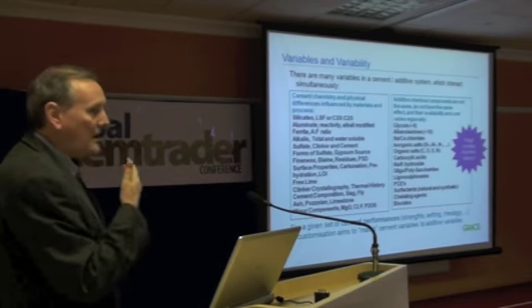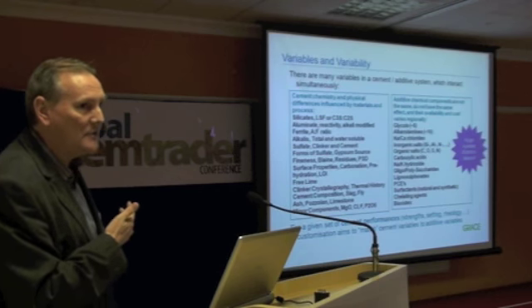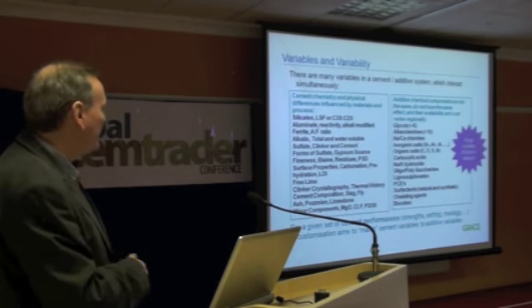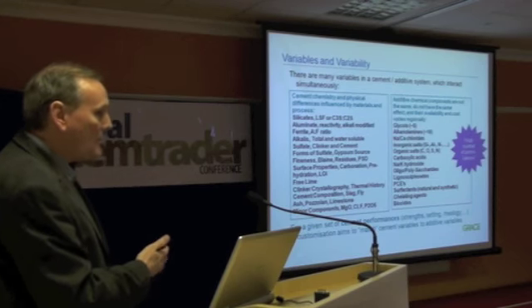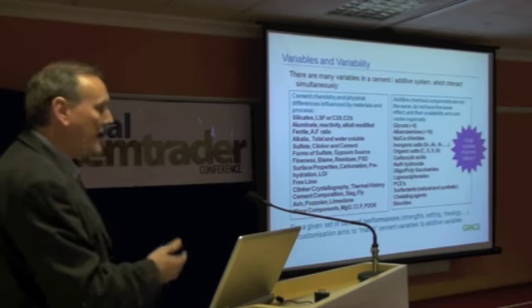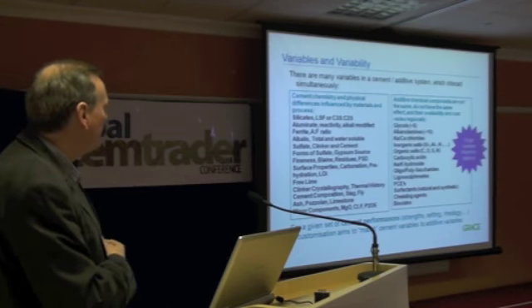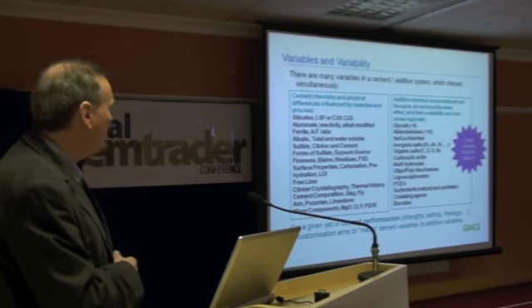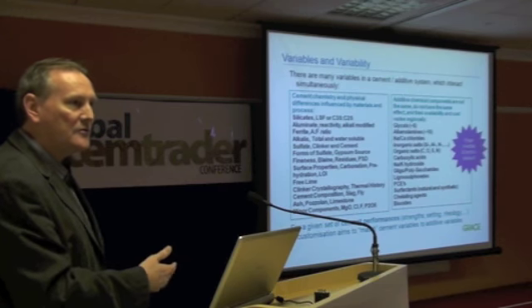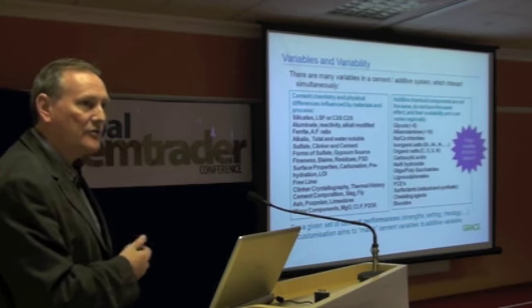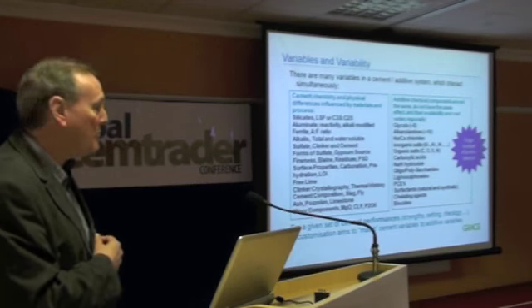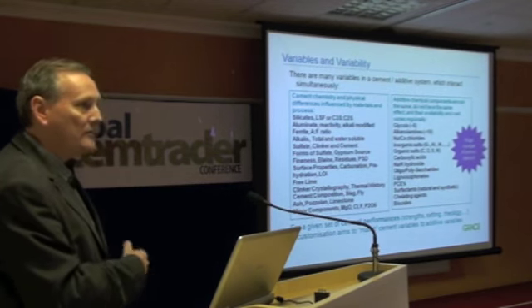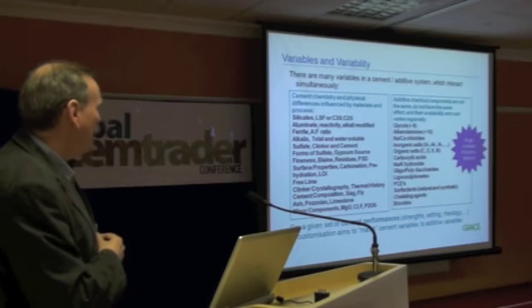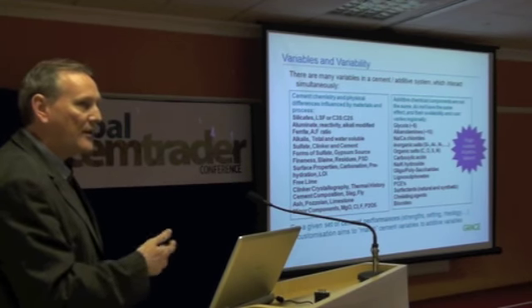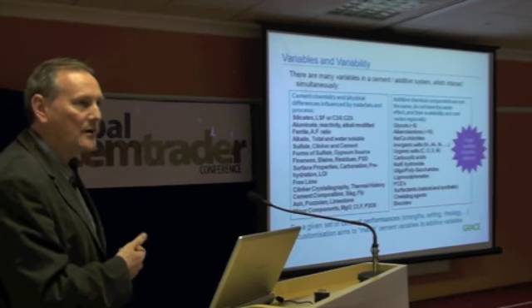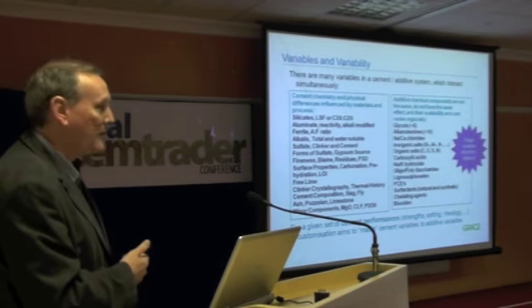But we're working in quite a noisy, variable environment. On the left-hand side, I've gone through the main cement variables. The main chemistry of the silicates, the aluminate and the iron, the alkalis. It's more complex than just the alkali level, it's the total and the water soluble. The sulfate is often just one number, but it's how much is in the clinker, how much is in the cement, what are the forms of sulfate due to the thermal decomposition that takes place in cement production, the fineness of the cement, really the particle size distribution, how the cement, when it's produced, has been pre-hydrated and exposed to moisture and carbonation. It affects the cement performance.